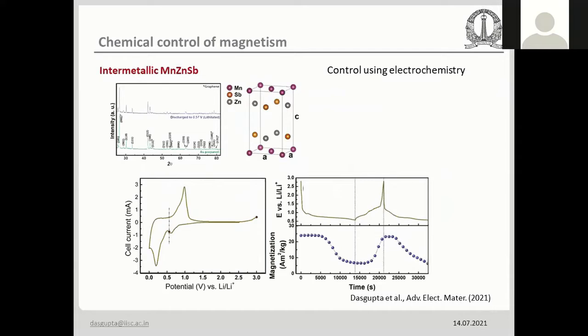But again we have done some electrochemistry. This little plot in the left hand side below is called cyclic voltammetry. Using this electrochemical method, typically for a battery, or in an electrochemical system, you can know exactly what is going on in the system. So using that, we again determined a suitable electrochemical potential, and here again we could get 75 to 80% control of magnetization.